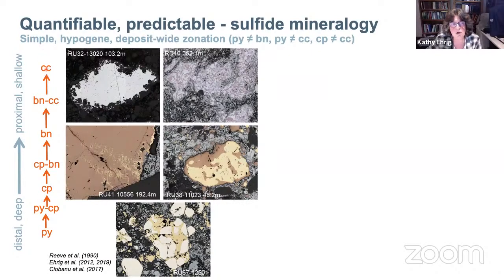And that there's really no, we don't see chalcocite ever touching chalcopyrite or pyrite. We don't see bornite touching pyrite. That shows us that there's a real simple hypogene sulfide transition going on. And that actually gives us a lot of predictive power. So as geologists, we recognize all these things. We can map out all these textures, or we can qualitatively map them out, but we can actually quantify them.